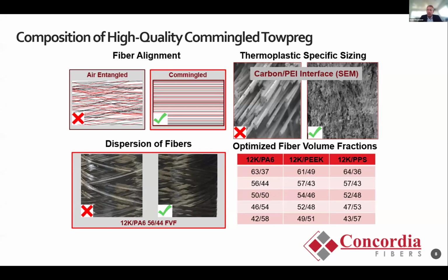The pair of pictures in the upper right show benefits or disadvantages of poor fiber matrix interface. So this is a carbon fiber PEI. And you can see in the left picture where the filament's pulled out of the resin, where there's poor interface, and then the image on the right shows very few fibers sticking out. So it's a great interface. These are the types of things that Concordia Fibers looks at to optimize the quality and the attention to detail we put into our commingling.